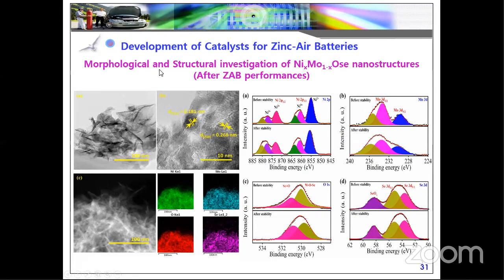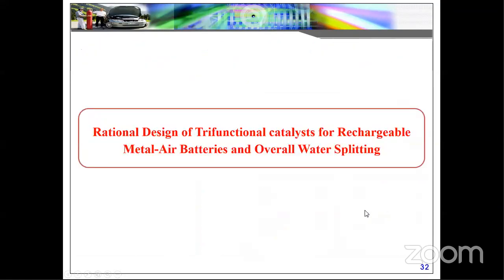Morphological. In order to prove the outstanding stability of the materials, we need to test the morphology. You can see the morphology, and the STEM EDS color mapping further confirms the selenium is almost retained after the long-term stability durability test. And the XPS, I already explained: the metal-based peaks shifted a little higher, not obviously, and the non-metallic ones moved a little lower. And finally, I already explained the bifunctional activity. That's why I gave one example for water splitting and another for the air battery.